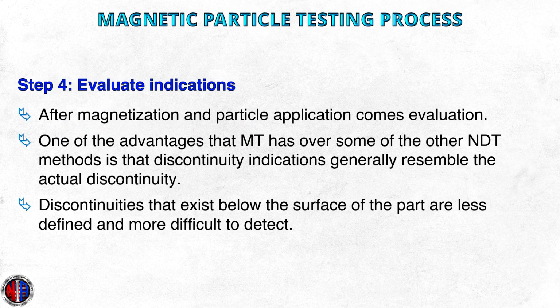Step 4. Evaluate and report indications. After magnetization and particle application comes evaluation. One of the advantages that MT has over some other NDT methods is that discontinuity indications generally resemble the actual discontinuity. Cracks on the surface of the part appear as sharp lines that follow the path of the crack. Discontinuities that exist below the surface of the part are less defined and more difficult to detect.